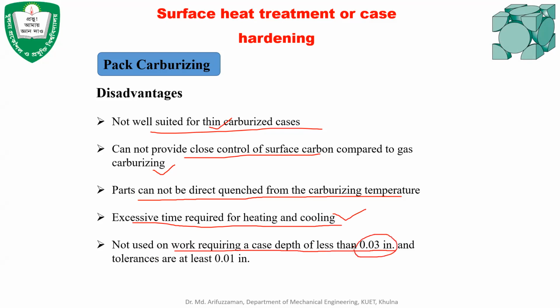If the case depth required is 0.03 inch with a very tight tolerance of 0.01 inch, then carburizing is not recommended because you cannot control the carbon diffusion into the material. Okay, any question for pack carburizing?